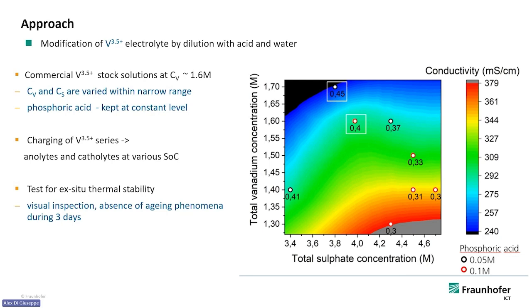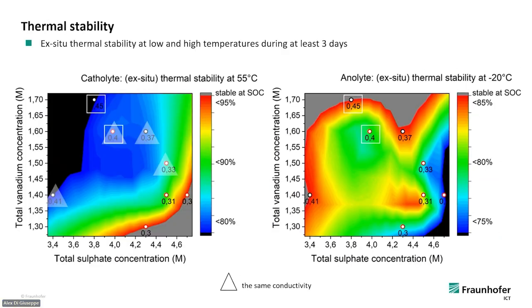So higher vanadium concentration usually means less conductivity. And so we made this ratio. This is always the number you can see below the dot. This is a ratio between the vanadium to sulfate content. And then we looked, we have black dots, which are with 0.05 molar of phosphoric acid as a stabilizer and 0.1 molar of stabilizer. And we made stability testing with all these compositions.